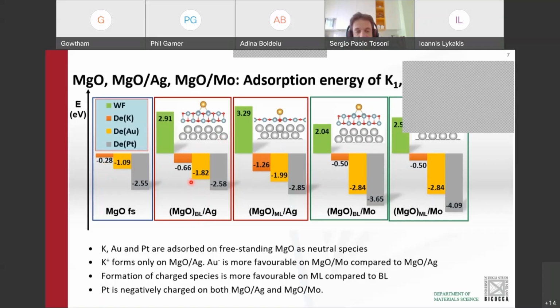Namely, potassium is ionized to potassium plus. An electron is transferred via tunneling effect to the metal substrate. And as you can see, we also have a strong increase in the potassium binding energy. And the larger the work function, the stronger the increase in the adsorption energy of potassium plus. This is due to the fact that large work function implies deeper acceptor states on the metal substrate. The metal is more prone to accept electrons if the work function is large.